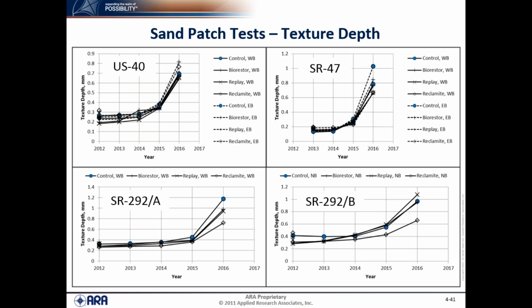What I'm going to do now is show you some overall results before I get into the comparisons. This is the results of the sand patch test in terms of texture depth in millimeters. The y-axis on each graph is the texture depth in millimeters from the sand patch, and the x-axis is time or year. US 40, upper left hand, shows an increase that really started in about 2016, and that was generally the case for the 292 sections as well as State Route 47. However, a texture depth of 1 millimeter, even though they're going up, is not significant. That's relatively low, so that doesn't indicate it's going bad.